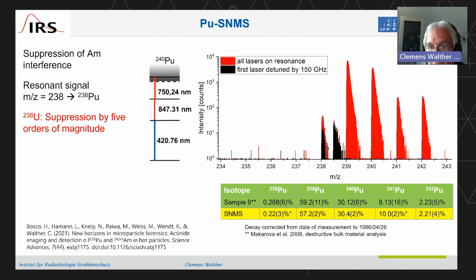Here, with the black peaks, we detuned the first laser, the blue one here, by 150 gigahertz, so that it's no longer in resonance and now hits just below this resonance state. That means the uranium is still ionized a bit non-resonantly, but the plutonium is not. That gives you the background contribution, and everything in excess here is the true plutonium-238 signal. That gives you a suppression of the uranium-238, which would be right at the top of the slide, by 5 orders of magnitude thanks to that very selective excitation scheme.